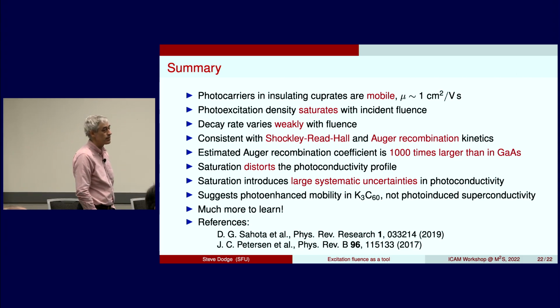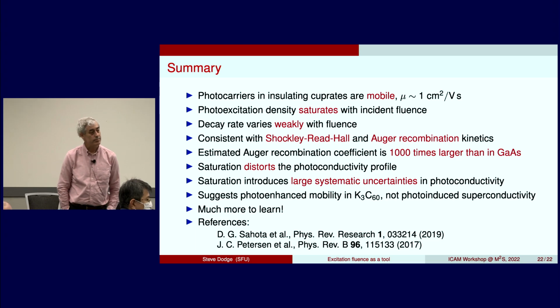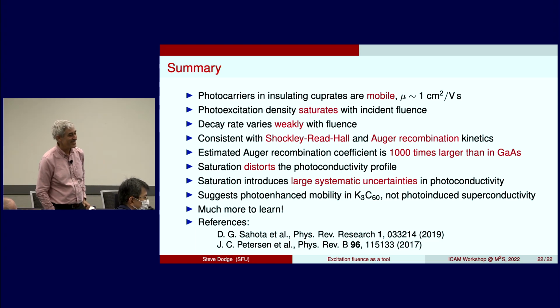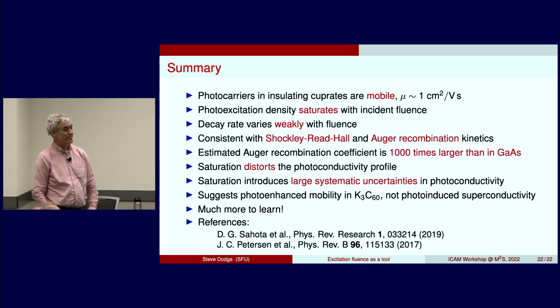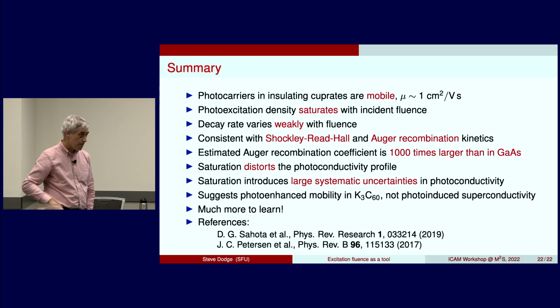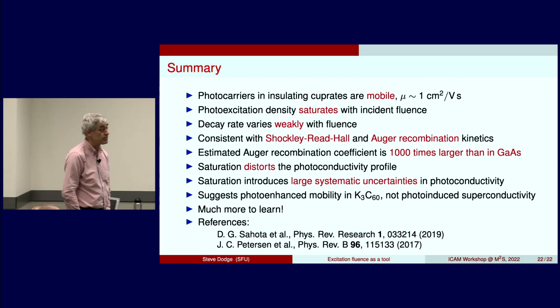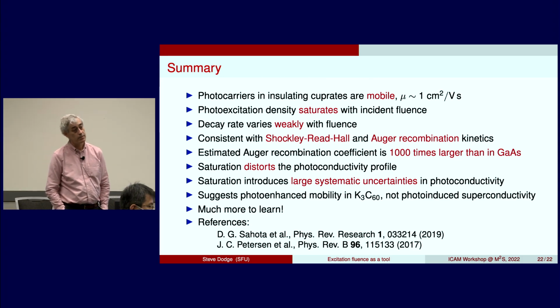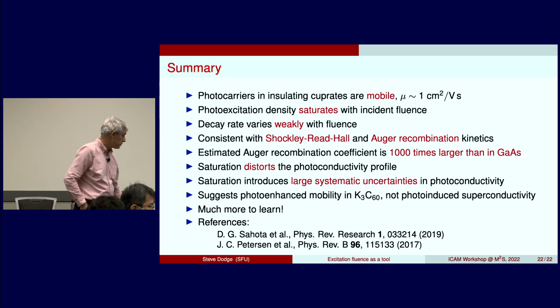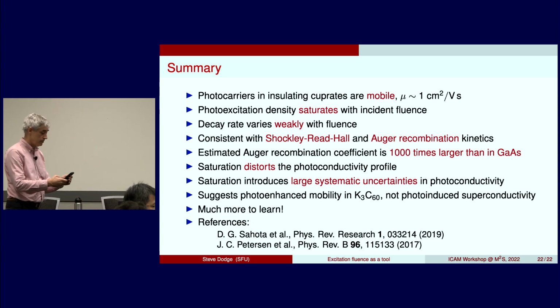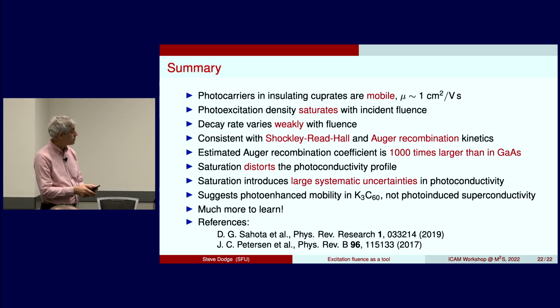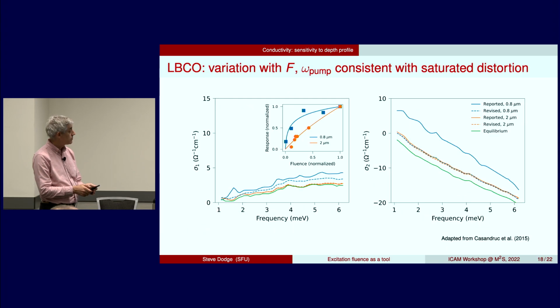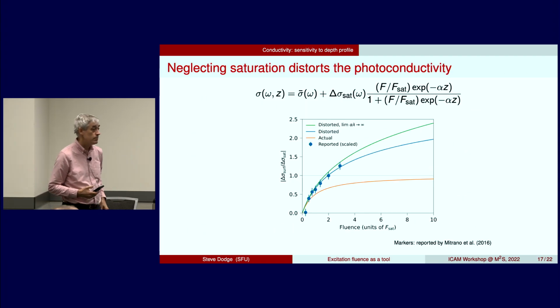Great. The reason why I think what you're saying is either not right or not unique is that when we were thinking about this problem, we were considering an effect that depends on the electric field, and not on the fluence. So if you're considering either a phononic effect or a Floquet effect, then a square root growth in the fluence is a linear growth in electric field. And if the underlying physics is an electric field effect, then what you're saying is not right.